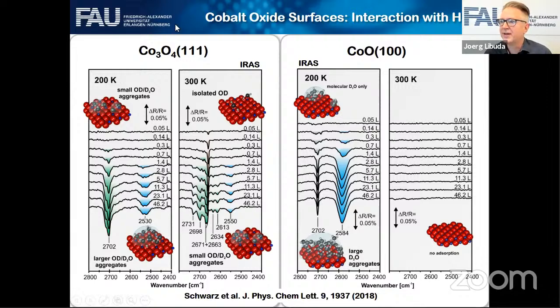So we adsorb water in an ultra-high vacuum environment. At room temperature, we look at the infrared spectrum exposed to water. Nothing happens. There's virtually no interaction with water at all. Water very weakly interacts with the surface. We can go to low temperature, and then we can condense ice multilayers or ice clusters on the surface. That's molecular water very weakly interacting with the surface. So in essence, this surface is totally inert. It doesn't like water. There's no dissociation, very weak interaction, super inert.